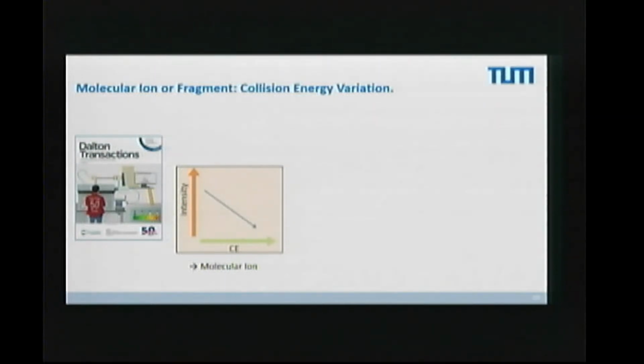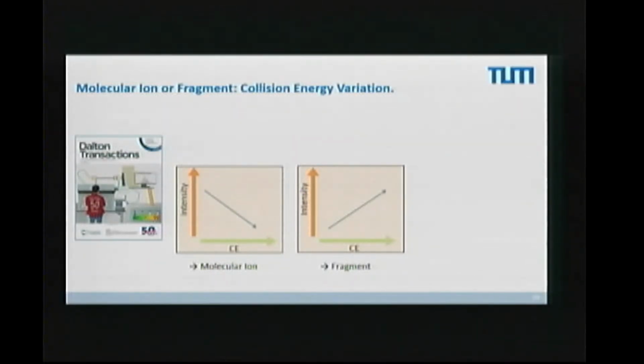If we have a molecular ion and we vary the collision energy, CE is collision energy, and if the intensity of the peak goes down, more collision energy, intensity of the molecular ion goes down because more fragmentation. Other way around, if the collision energy is going up and the intensity of the peak we are testing is going up, it must be a fragment.